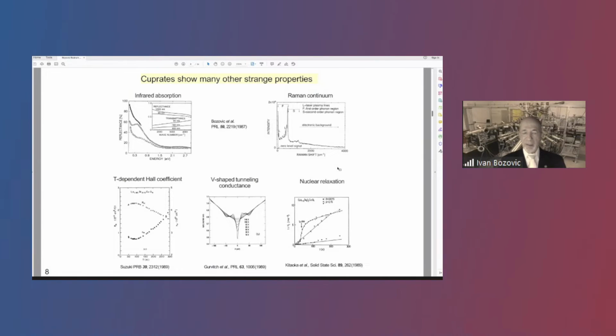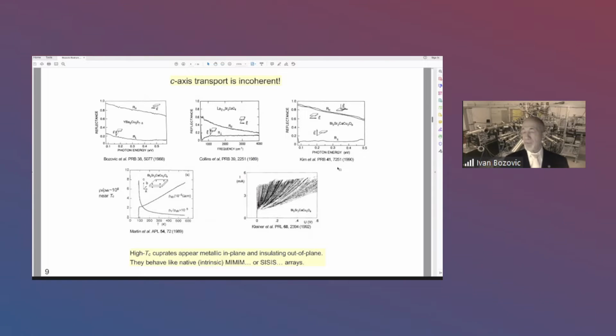And what that tells you is that actually the quasi-momentum is ill-defined or completely smeared out. And there are these other probes that I will not comment upon, but basically, whichever other way you probe it, the normal state, normal metallic state in cuprate is everything but normal. And this was in plane.